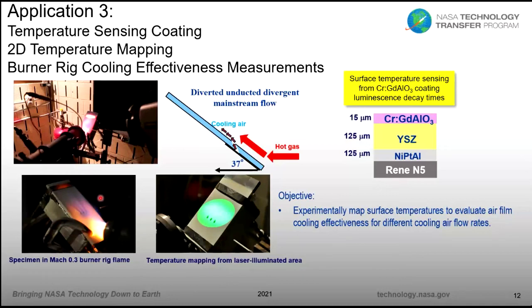One of the advantages of having such a strong luminescence emission is that we don't have to raster a small laser beam across our whole surface. We can just expand that beam, even though it's a lot lower in intensity per square centimeter, and we still get enough to do our mapping. So you can expand it to an area like that, and we'll get a map over that full area.